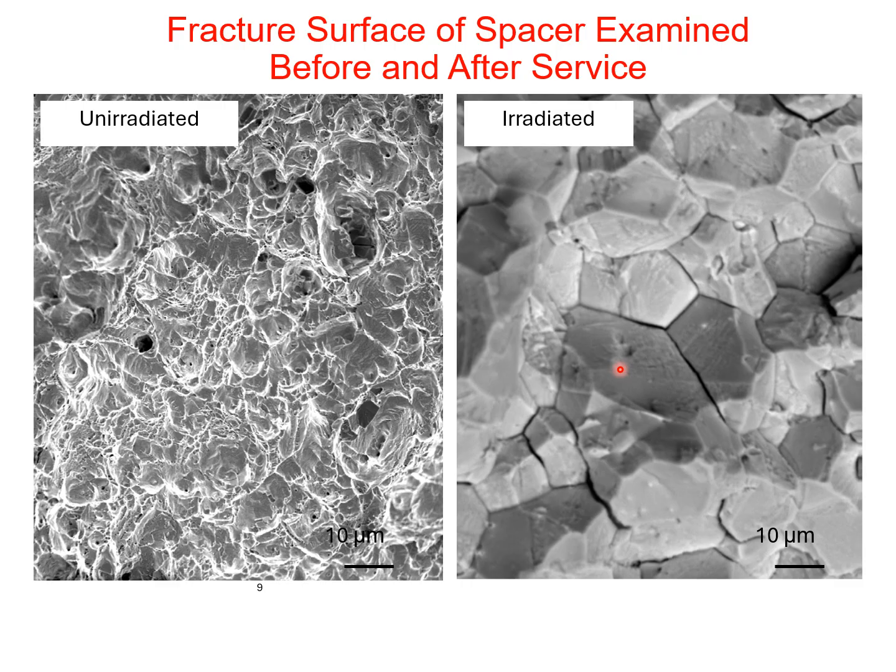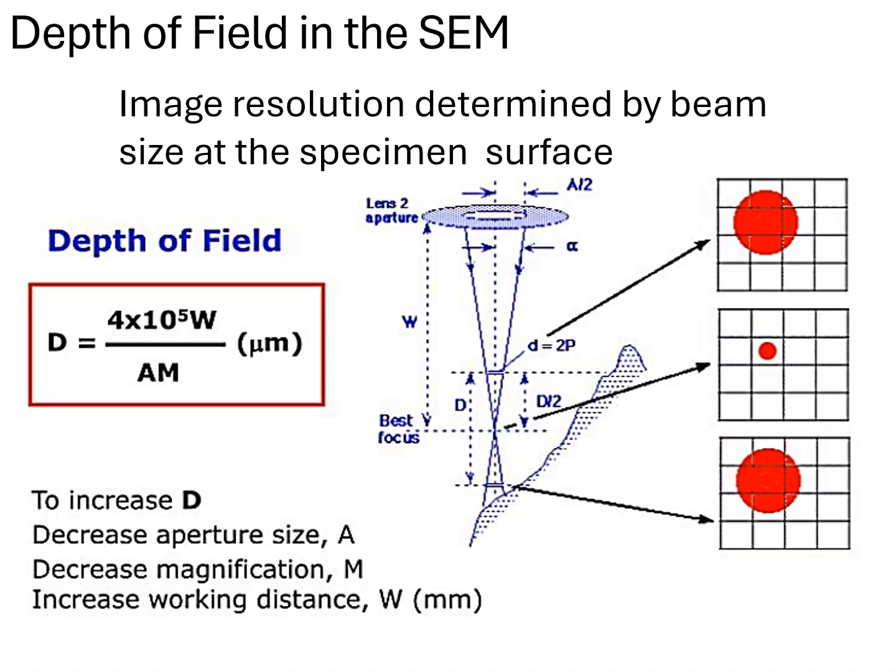Because all those bubbles are helium-filled bubbles, and helium doesn't get absorbed by grain boundaries, it tends to sit on grain boundaries and stabilize cavities there. You tend to get a lot more intergranular fracture when you have helium bubbles in a material. Now, in this particular case, the image is quite nicely focused here, but it's a little bit fuzzy off to the edges. And partly that is because it has a different height, and depth of field becomes important.